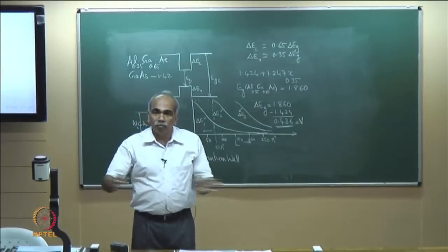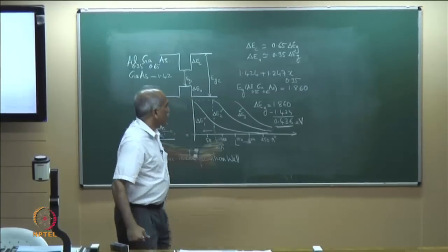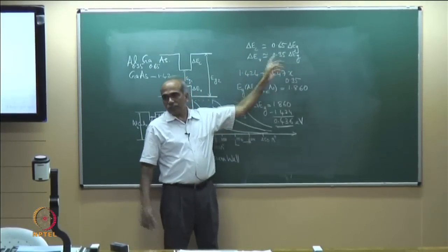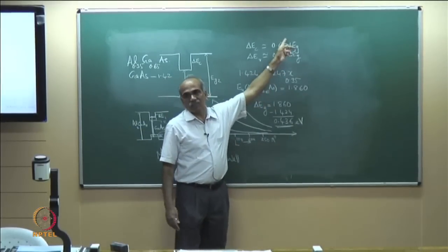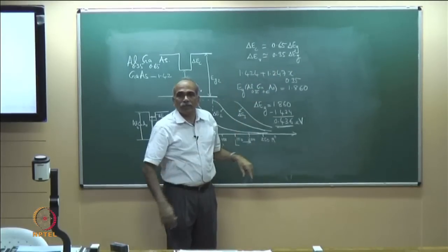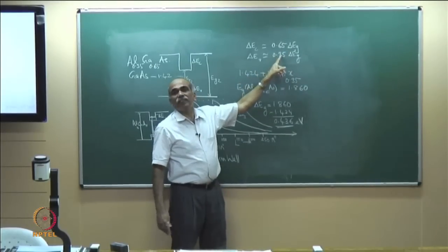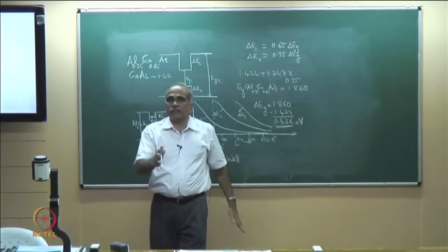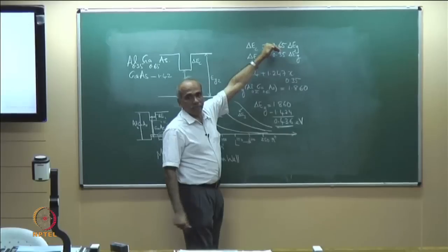Why this is a bigger issue. So this depends on the material. The question is whether this 65 and 35 is universal for all materials. No, it depends on the material system, but for most materials used in optoelectronics, it is approximately in this region. Sometimes you will see 33 and 67, or 30 and 70, but it is around this value, and it depends on the material system.